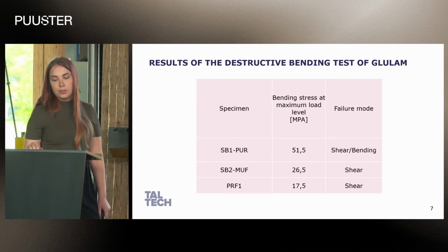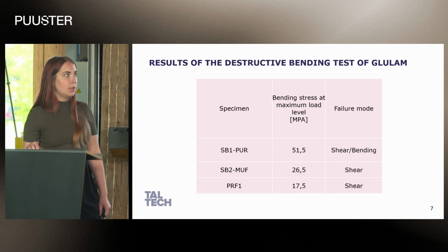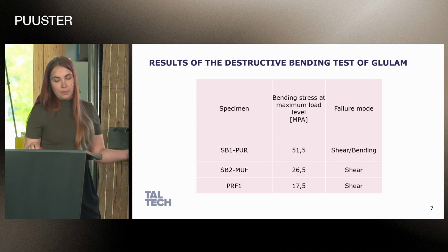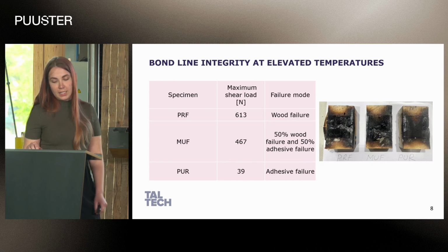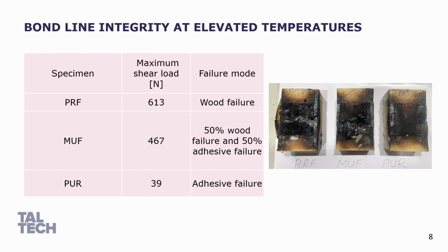The reason for the shear failure in the bond line was the uneven surface of the lamellas caused by the cutouts, rounded corners, and the glulam manufacturing method. When testing the bond line integrity at elevated temperatures, the best result was achieved by the specimen bonded with PRF, which exhibited only wood failure as shown in the picture.